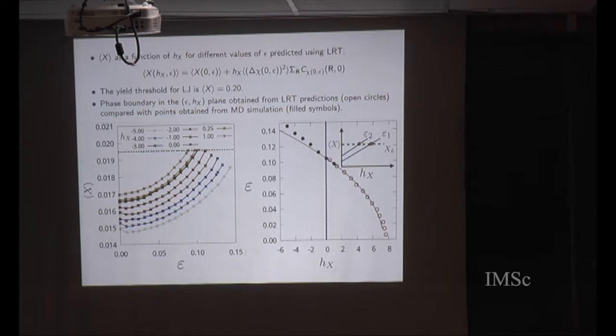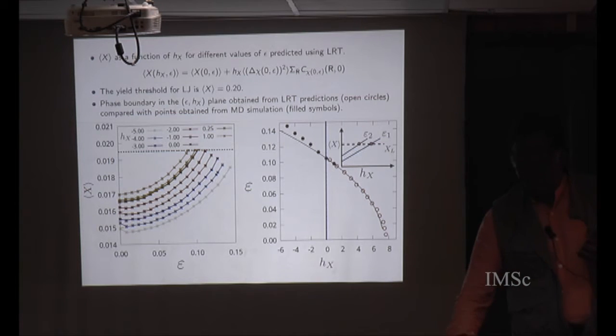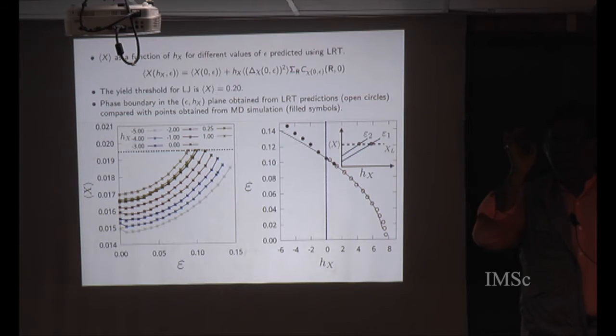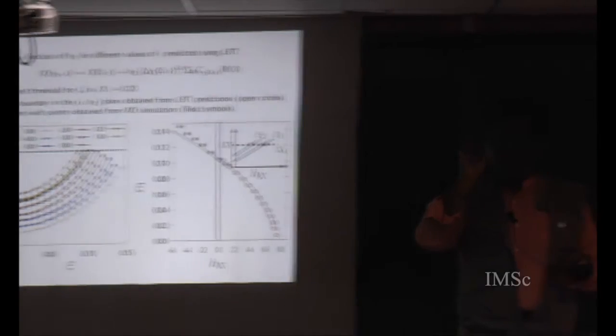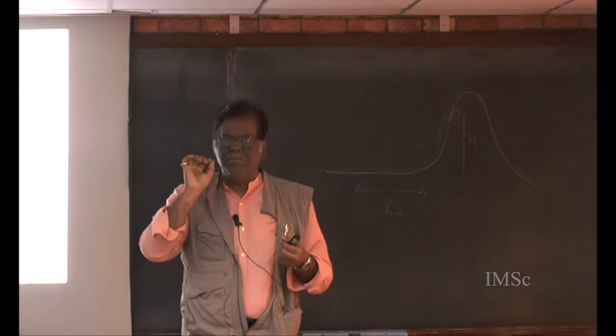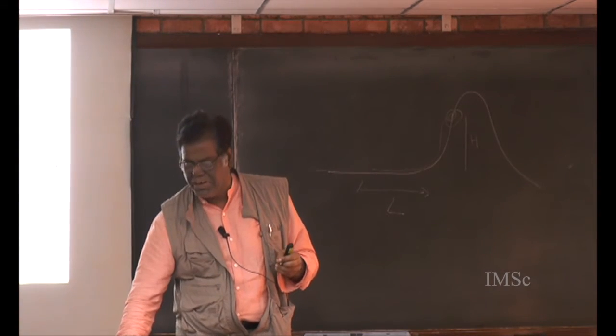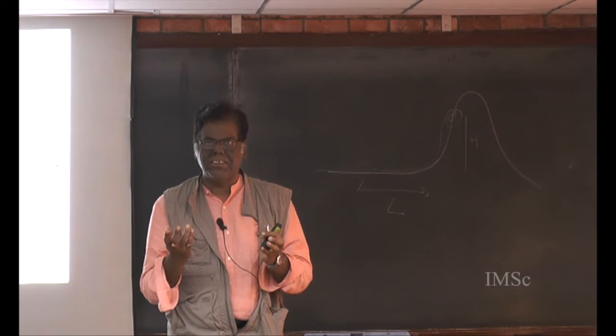Because this transition, this dynamical transition as a function of h or as a function of strain, is the same transition. So this is the main point of this entire study. And this is remarkable because you can now predict yield points from a Lindemann-like criterion. One parameter, which one can calculate for various interactions.